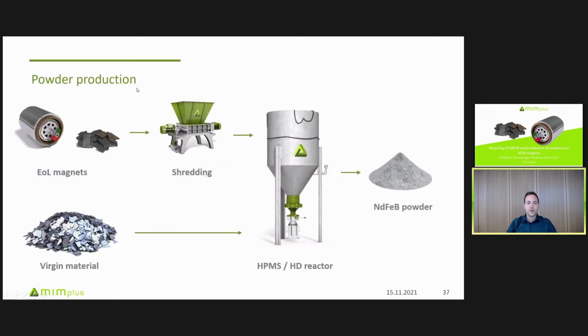I'd like to start first with the powder production. We start, for example, with end-of-life magnets. You have to extract the end-of-life magnets, for example, by stamping these out of electric motors or by shredding smaller assemblies to extract the magnets out of them. Then they are transferred into an HPMS reactor where the so-called HPMS reaction follows, as Carlo introduced earlier, and I will show you on the next slide again. And then you get the clean NdFeB powder. A second approach is to use virgin material, where you directly feed the virgin material into the hydrogen decrepitation reactor, and you also get clean, fine neodymium iron boron powder.